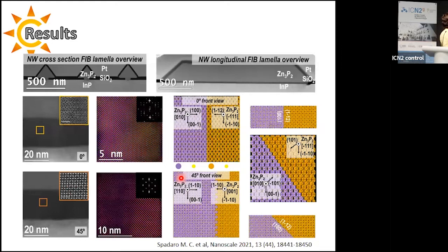Looking into more detail the structure of the nanowire itself all along the length, we could observe both from STEM HAADF image contrast and power spectra analysis that the material presents secondary domains, here depicted in orange, that are related to the zinc phosphide growing in a rotated direction with respect to the main domain, which is in violet. And with further study, we could evaluate that this type of domain appears at the early stage of growth.